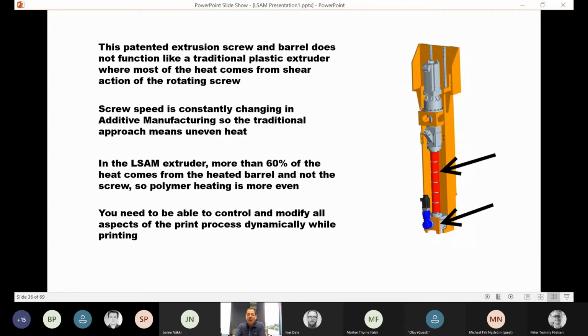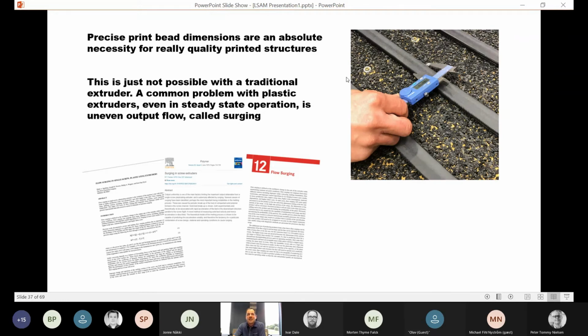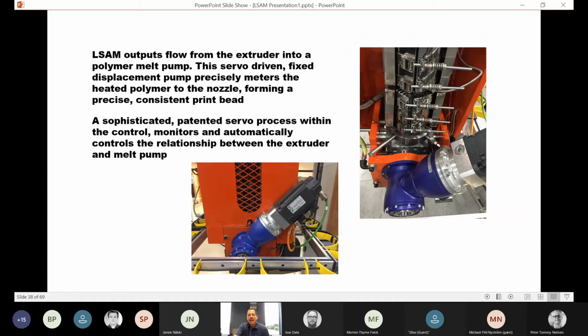You need to be able to control and modify all aspects of the print process dynamically while printing. Precise print bead dimensions are an absolute necessity for really quality printed structures. This is not possible with a traditional extruder. A common problem with plastic extruders, even in steady state operation, is uneven output flow, called surging. The LSAM outputs flow from the extruder into a polymer melt pump. This servo-driven fixed displacement pump precisely meters the heated polymer to the nozzle, forming a precise, consistent print bead. A sophisticated, patented servo process within the control monitors and automatically controls the relationship between the extruder and the melt pump.